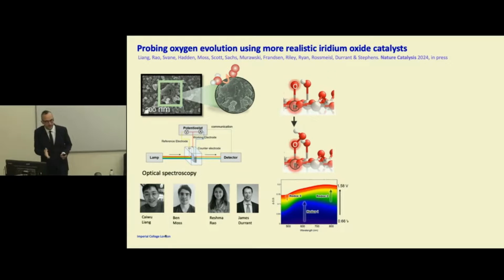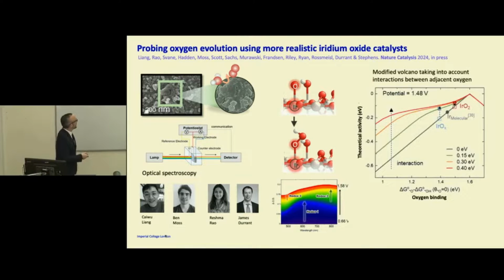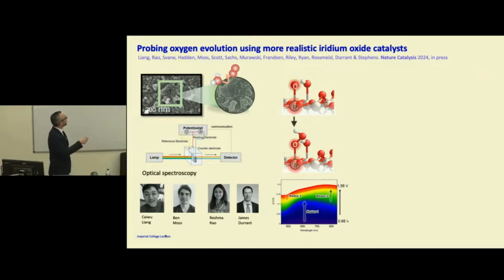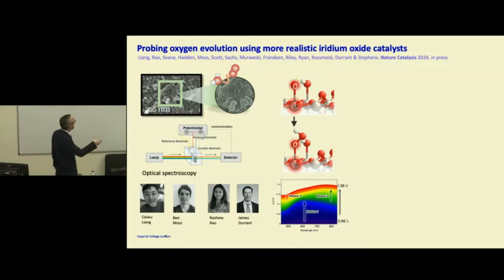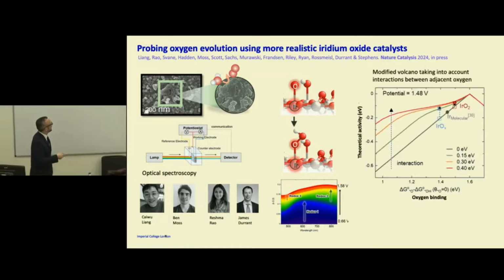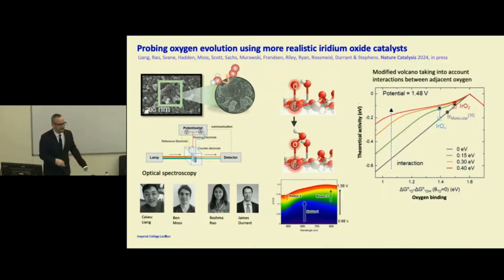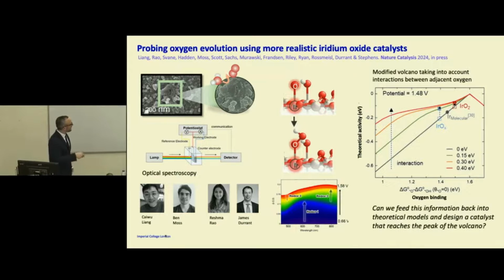And as I mentioned previously, that's what we think controls the performance. But what we found is that what really controls the performance is not just how strongly it binds, but how much these different intermediates interact with each other. They tend to repel each other a bit, and we could tell all that from looking at these spectra. So it was really fascinating. And then we ended up making a new volcano. You can see the strong-binding side of the volcano became a lot flatter than before, which is very exciting. These are brand new results. Ideally, we're now at the point where we can benchmark. Previously it was very difficult to benchmark the actual experiments against theoretical calculation, but now we can do that.